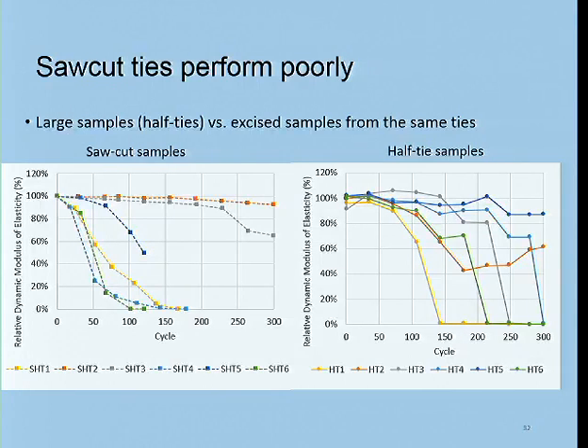And one of the most important findings is proving that anything cut from a precast member that involves cutting through the steel is problematic. We routinely saw worse performance in these saw-cut samples than we did in some of the related half-tie samples. Here we saw some problems as well, but much quicker decay of the freeze-thaw performance in the saw-cut samples.